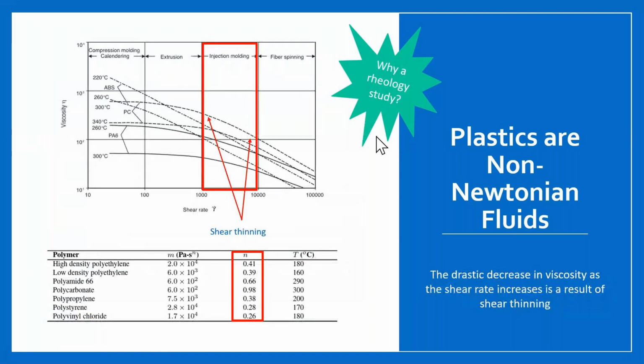Another way to think about this is polymers are non-Newtonian. A Newtonian response would be a linear response between shear rate and viscosity, while a non-Newtonian is a nonlinear response. We can see here several different standard polymers, ABS, polycarb, nylon 6, and we're showing 4 different what we call shear rate regimes. Very low shear rates for compression molding and calendaring, a little bit higher shear rates, and this is a logarithmic scale for note, a little bit higher shear rates in extrusion. Injection molding, we have middling shear rates, and then in fiber spinning, we have high shear rates.